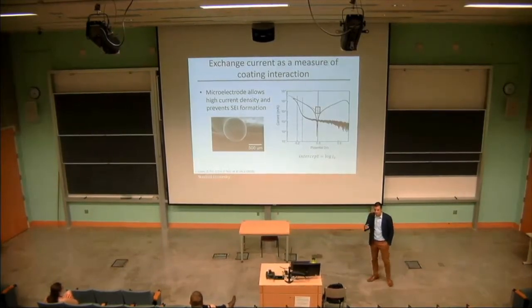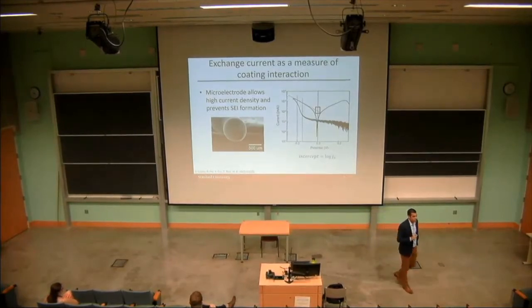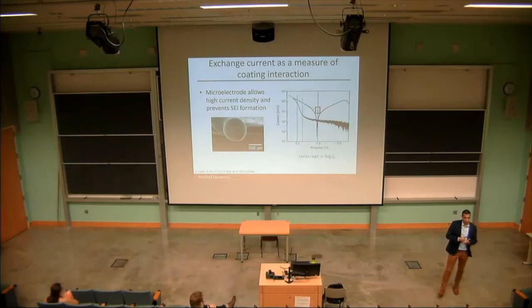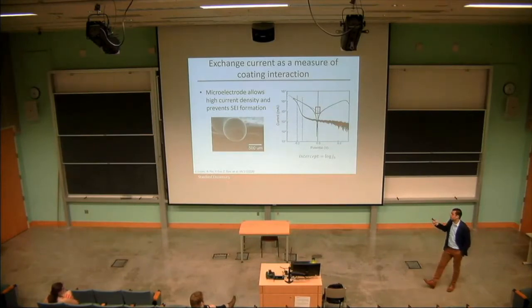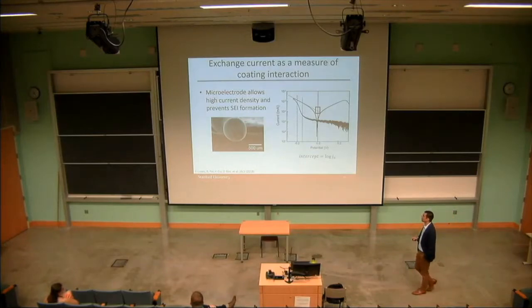The reason that exchange current is pretty difficult to measure for lithium systems is because we want the exchange current of lithium in the presence of the polymer coating. But as I mentioned before, lithium's highly reactive. And so we have to scan very, very quickly to get a pure CV that doesn't have any sort of influence from these electrolyte decomposition products that form. And when you think about the high rates that we need to get a scan that fast, we have to use very, very small electrodes to make that achievable with our instrumentation.